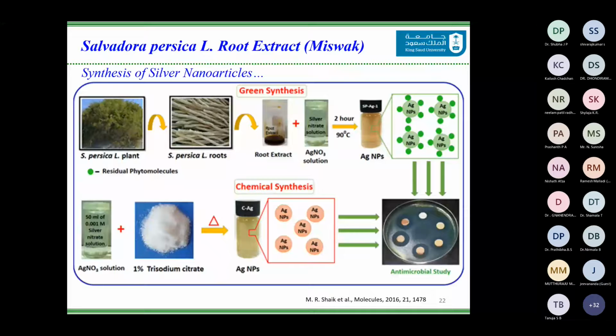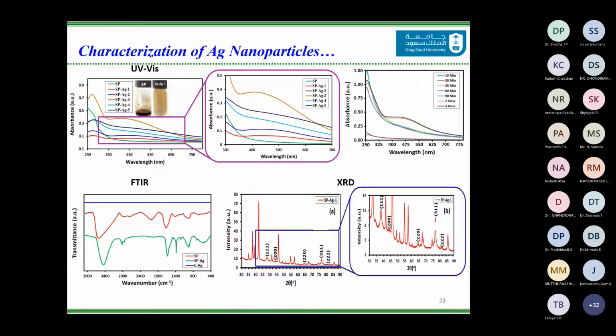Just to keep it brief, as we have already seen, the silver nanoparticles have a signal between lambda max 380 to 450. And what we have done is we have used varying amounts of root extract for the synthesis of the silver nanoparticles. And we have done this reaction at 90 degrees centigrade, and we found that the reduction of silver nanoparticle is complete within 2 hours.